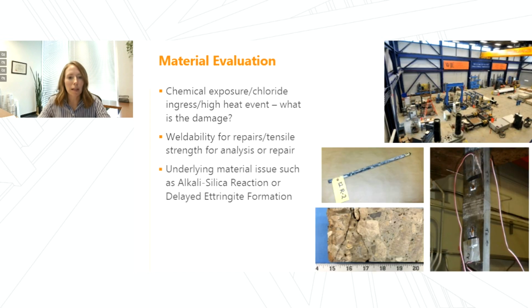Another example is material evaluation. So you may know you have a material degradation exposure, but you don't really know what the extent of your damage is. As shown in the previous slide, where along the chloride profile you have in your concrete can tell you a lot about the potential damage. So if you take some concrete cores, you do a chloride assessment, your concrete covers 2 inches and you only have chlorides at 1 inch, okay, well that tells you we don't really have a concern in certain elements. If it tells you, hey, no, we're at the level of the reinforcing, well then that maybe can be part of your preventative maintenance plan.